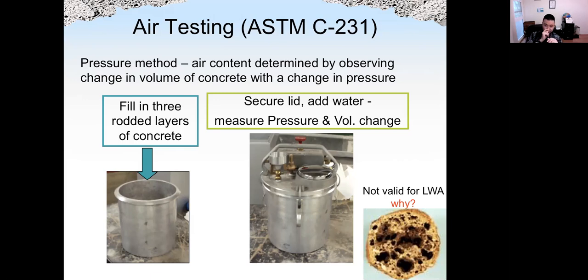If we use a lot of lightweight aggregate in the concrete, and when we do the pressure type of air testing, the air inside the aggregate will also be compressed. So that will overestimate the percentage of air in concrete, because we only care about air inside the cement paste and not air inside of the aggregate. So remember, the pressure method is not valid for lightweight concrete with lightweight aggregate.